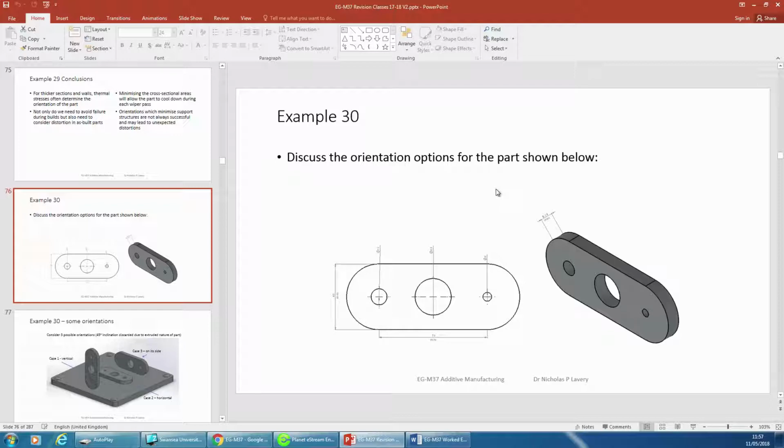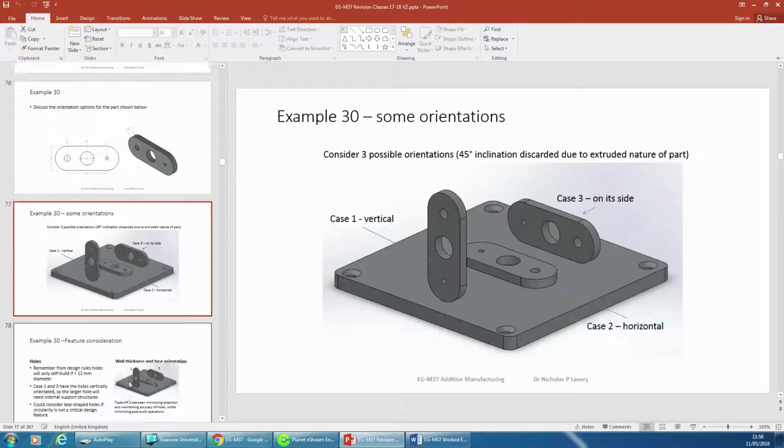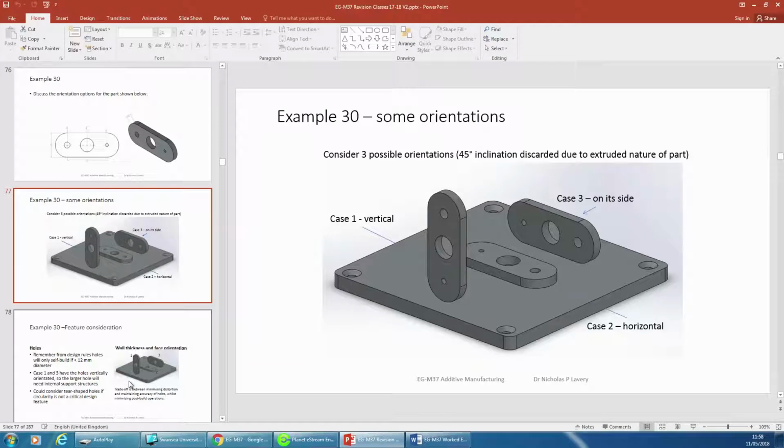If you give that to me in an exam question and say 10 mm is the smallest hole that I can build, I'll be happy with that. Although you have seen that by modifying the hole you can build bigger holes, and it's not always that you can build small holes. So you'd have to probably do some testing of the material. But as a rule of thumb, 10 mm diameters will self-support.